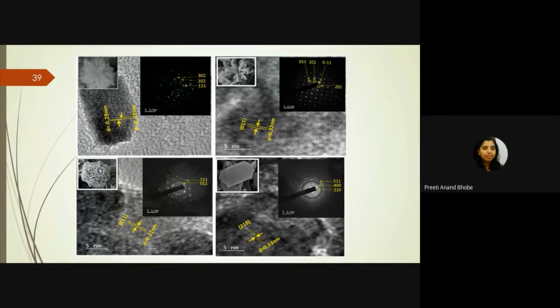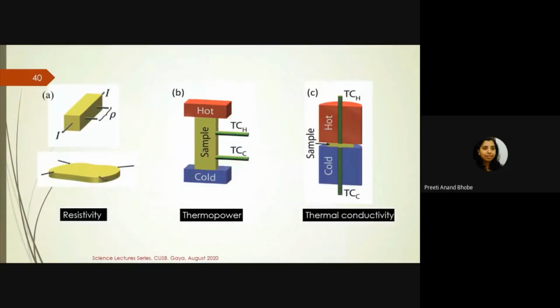Then what happens to the thermoelectric properties? Because that is what is interesting. But for that, I need you to know that when you want to measure the thermoelectric properties, there are three parameters we are measuring: the resistivity, thermopower, and thermal conductivity. In all these measurements, I have to take my sample powder, grind it, and make a strong pellet, and that pellet should be dense enough. It should be strong. There should not be any voids or empty gaps or air. It should be a nicely densely packed pellet.